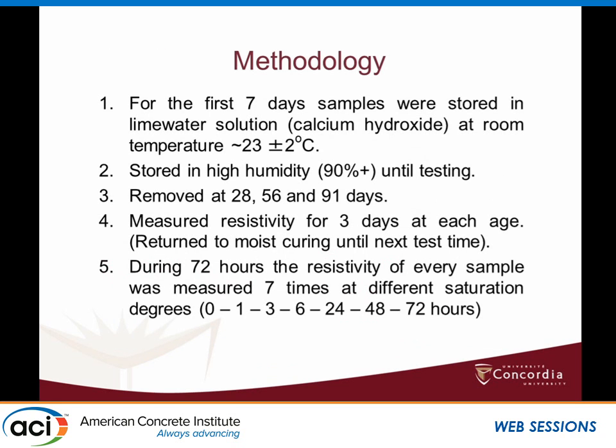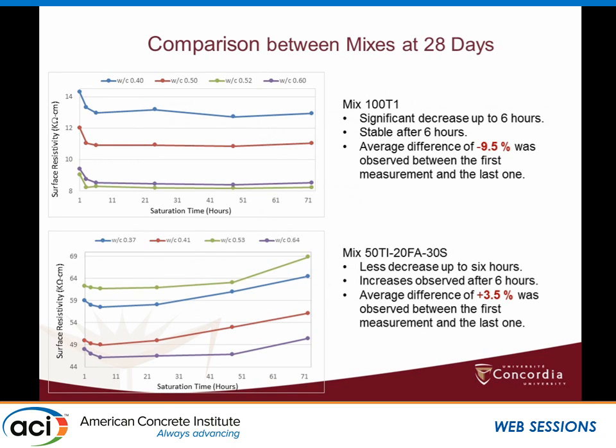So we cast, for the first 7 days, we stored these samples in lime water according to the AASHTO standard procedure. And after that, we remove the sample and we measure for 3 days at different times, different hours. So we start like, okay, what happened when you put the sample in 1 hour saturation? What happened 3, 6, 24, 48, 72?